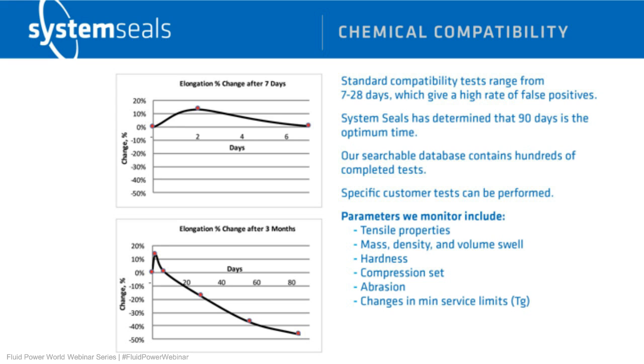What this means is that according to a 28-day test, this material fluid combination would still be deemed compatible, but if we look at the curve over 90 days, we see that there's a continual downward trend, and this particular property drops off to almost 50% of its original value. And by most standards, and by our internal standards, this is not a material fluid combination that we would consider compatible. It is certainly not optimum.